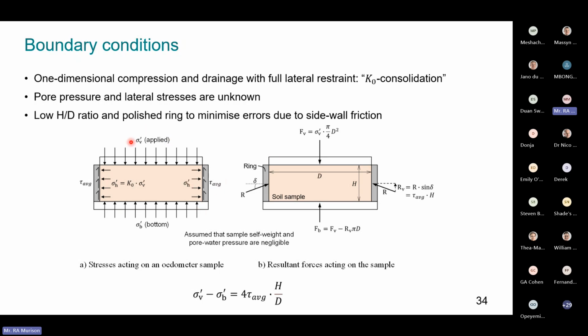And what we see here is that we have an applied stress to the top of the sample not being equal to the stress recorded at the bottom if any shear stresses are mobilized at the interface between the odometer ring and the soil. And a difference in top and bottom vertical stress would result in a conformance error. We'd be under-measuring the compression because not all of the effective stress is being transferred to the bottom of the sample. So given these assumptions and free body diagrams, we can actually determine an expression for the difference between this top and bottom stress. And we see that it's a function of the average shear stress mobilized along this interface and the H/D ratio, the aspect ratio of the odometer sample.